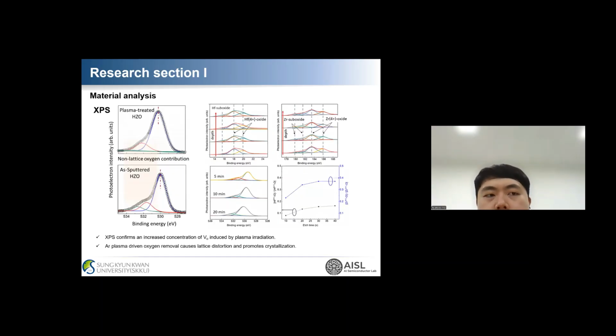We further analyzed the plasma-treated HZO samples using XPS. In the case of argon plasma, the kinetic energy induced reduction of hafnium oxide and zirconium oxide in HZO, leading to local structural distortion. This structural distortion promotes crystallization, and we confirm that the resulting phase is the ferroelectric orthorhombic phase. During this process, oxygen vacancies are also generated within the HZO structure. It is well known that oxygen vacancy concentration plays a key role in phase formation in HZO. Therefore, we suggest that plasma-induced oxygen vacancies directly contribute to the formation of the orthorhombic phase.